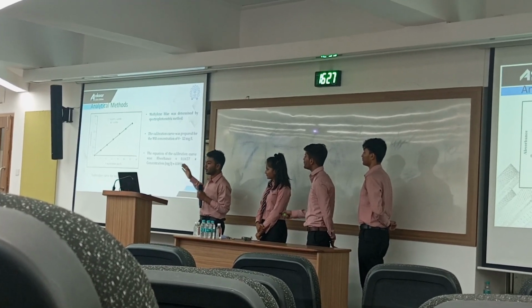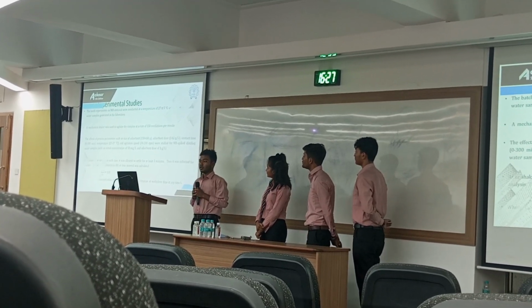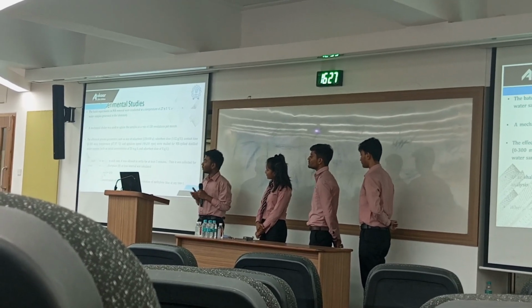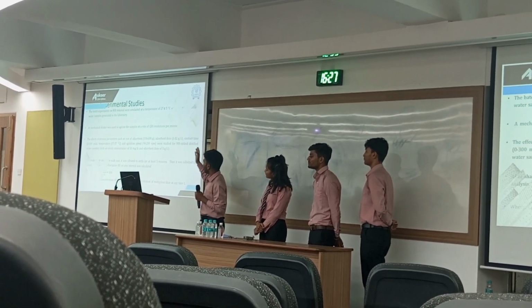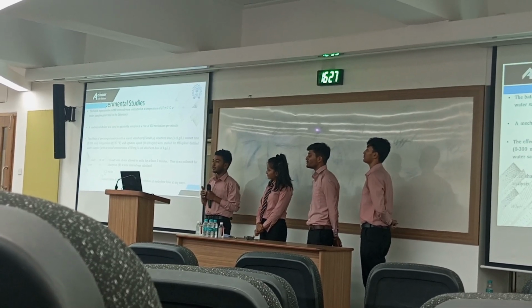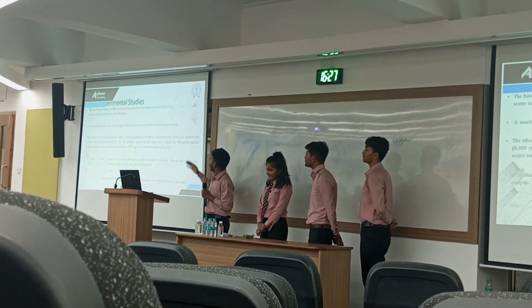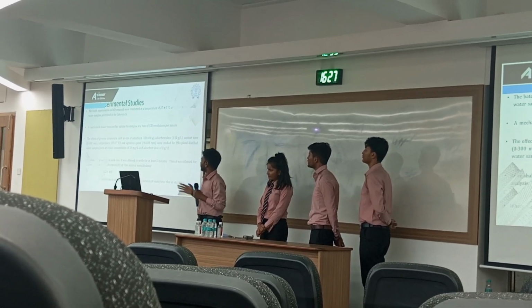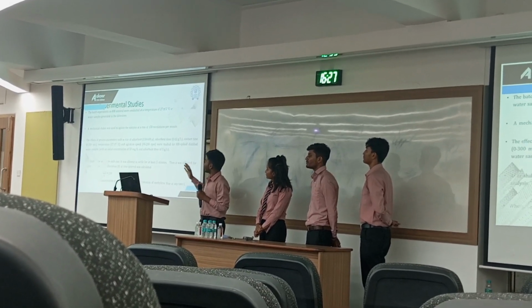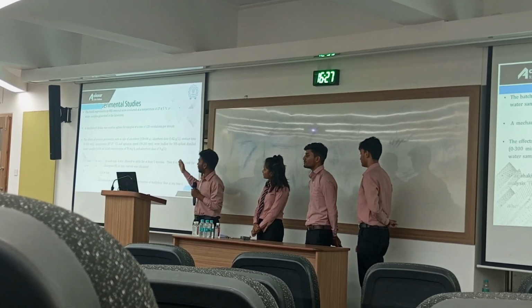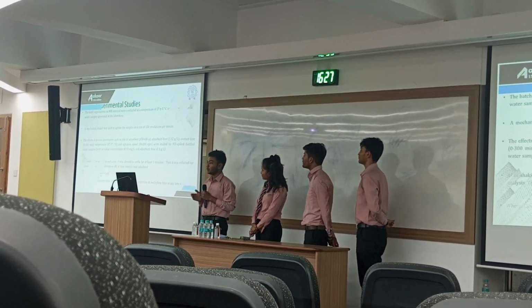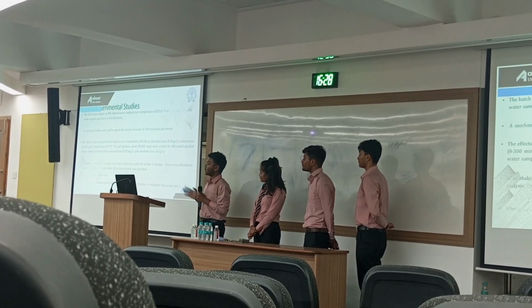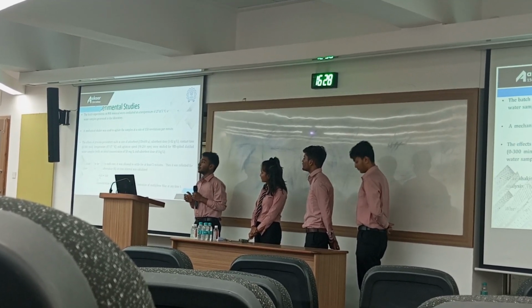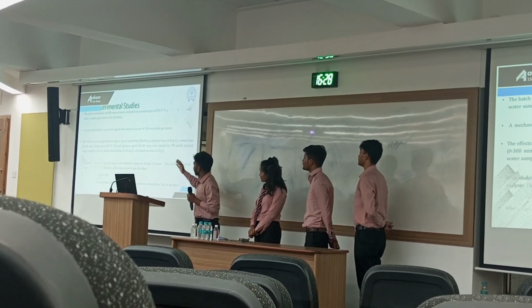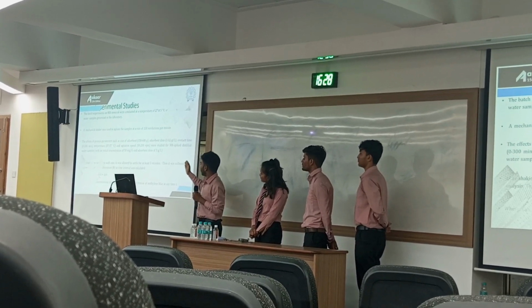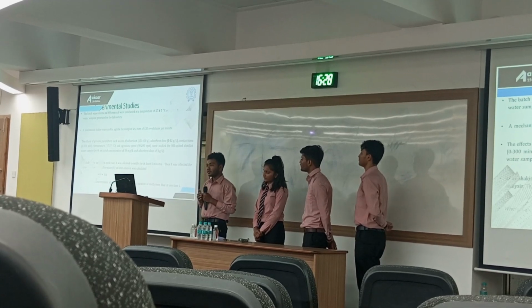Now the procedure of removing methylene blue from the aqueous solution. At first, we make a methylene blue solution with the help of distilled water at a temperature of 27 ± 5 degrees centigrade. Then we mix the adsorbent material and methylene blue in a mechanical shaker at a speed of 150 rpm. There are some parameters which affect the adsorption. The size of the adsorbent should be between 150 to 600 micron, the adsorbent dose between 1 to 12 gram per liter, and the contact time between 0 to 300 minutes. The temperature should be between 27 to 37 degrees centigrade with an agitation speed of 90 to 200 rpm.